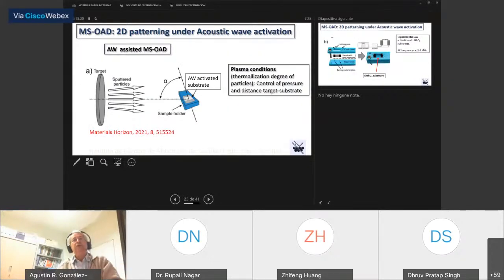Well, let me show you the experimental conditions of our experiment. We have a target. We have a piezoelectric substrate here, which forms a certain angle with respect to the track of the magnetron sputtering source. Of course, everything I have said about the control of the pressure, in order to control thermalization, pressure and target-substrate distance, has to be very carefully controlled to get a good result for this experiment. I will not go into this detail, but just bear in mind that that is very important. Otherwise, we will not get the result which I am going to show you.